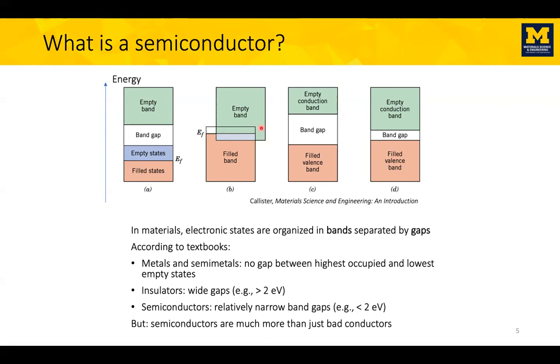Again, here the bands are fully occupied, but because they overlap in energy, you still have a Fermi level. In contrast, the insulators are characterized by a band gap, meaning that the highest occupied state and the lowest empty state are separated in energy by an amount on the order of eVs or more. In this situation, if you apply a field, you will not get conduction, right? Thermal energy is not enough to excite electrons across this band gap. And so that would be an insulator. Think of silica, think of glass or sand.